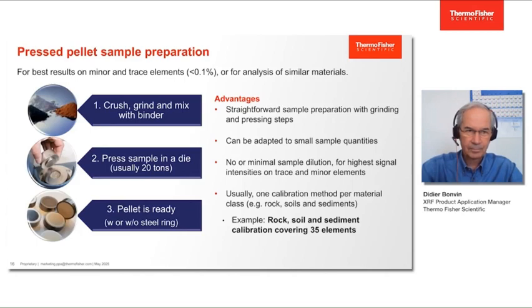The first one would be press pellet sample preparation, because it would provide the best performance for minor and trace elements. When we talk about trace elements, it's less than 0.1% or less than 1000 ppm, or also for the analysis of similar materials. So the preparation is done first by crushing, grinding, and then mixing with a binder if necessary. Second step is to press the sample in a die.